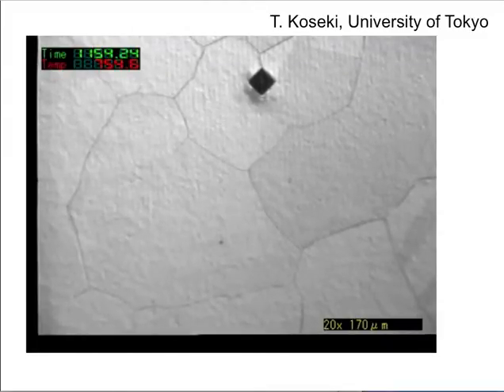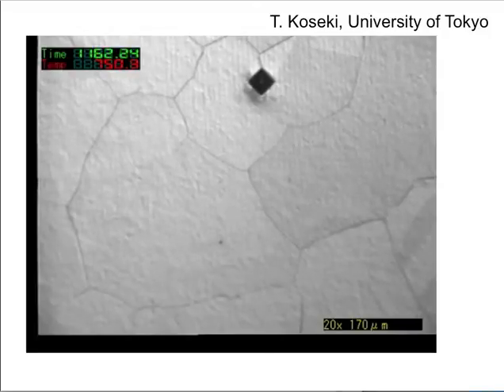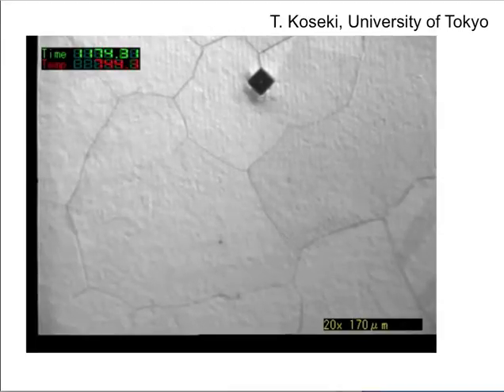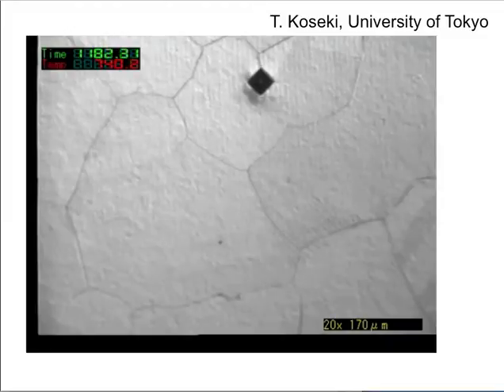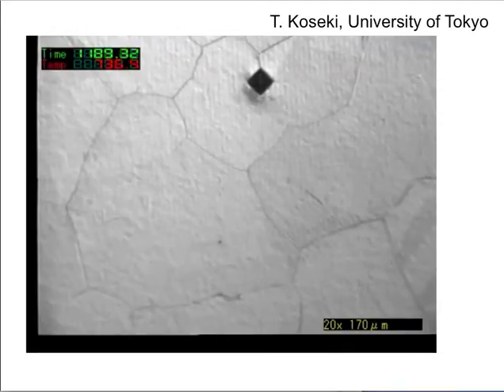The temperature is now 755 and this is a 0.15 carbon alloy, so we should have formed ferrite by now. Because of the absence of any shear deformation, you also do not have the vast strain energy that is associated with the invariant plane strain shape deformation. There is nothing to see in terms of surface relief - if I do that, can you see in this region a small change in contrast? That is the ferrite growing.